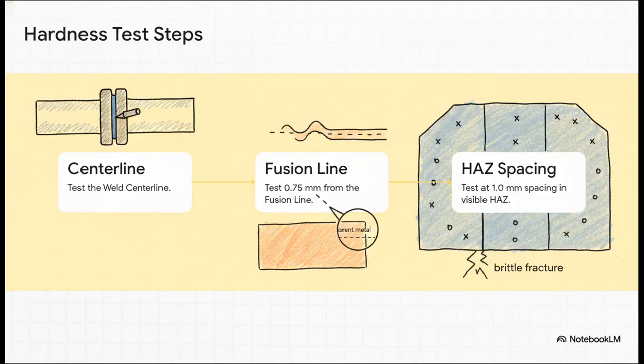The level of precision required here is just fascinating. Step 1, testers have to indent the exact weld center line. Step 2, they move precisely 0.75 millimeters into the parent metal. And step 3, they test at exactly 1.0 millimeter spacing all throughout the visible heat-affected zone. It might sound like a bunch of abstract rules, but this standard forces an incredibly thorough investigation into a notorious hotspot for potential brittle fractures.